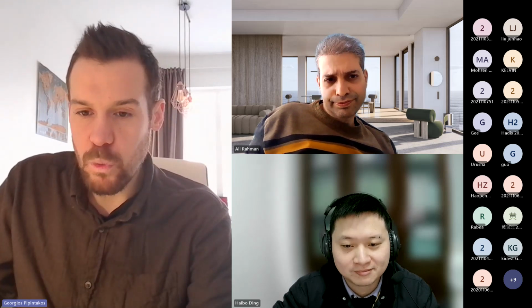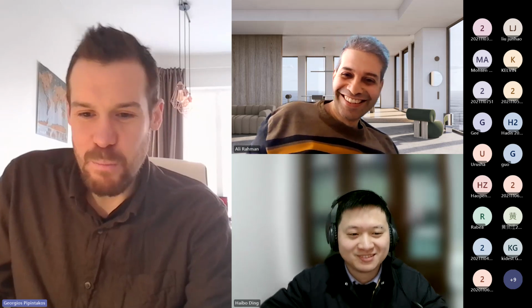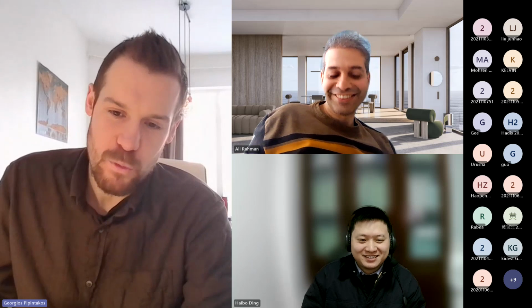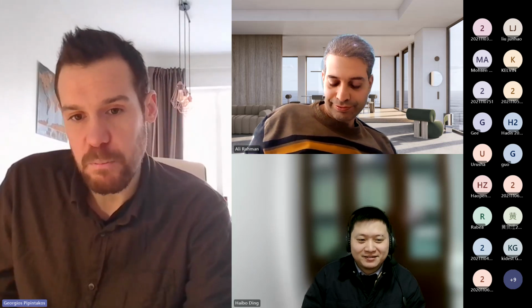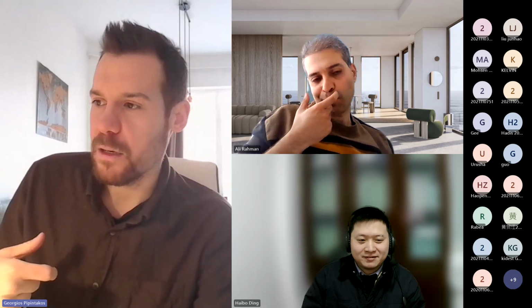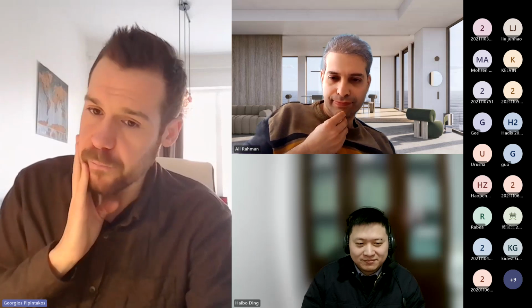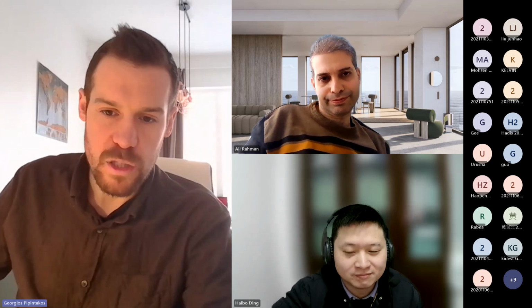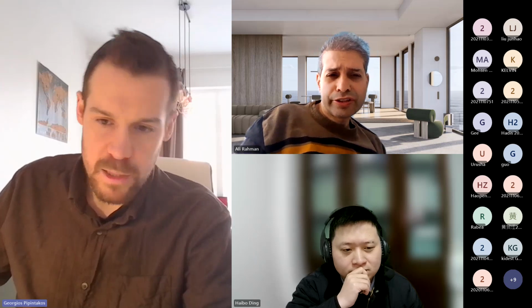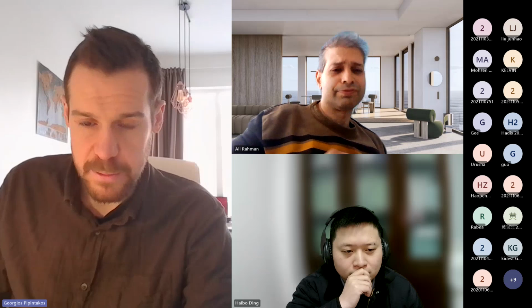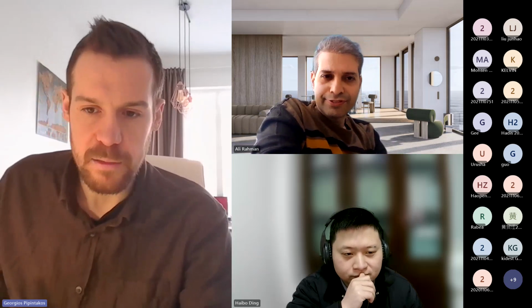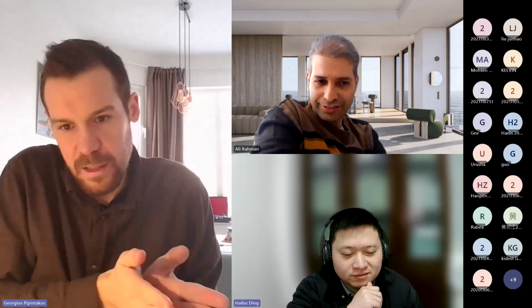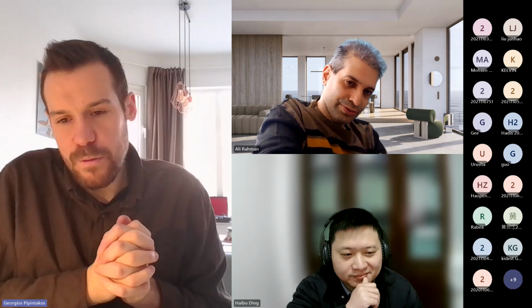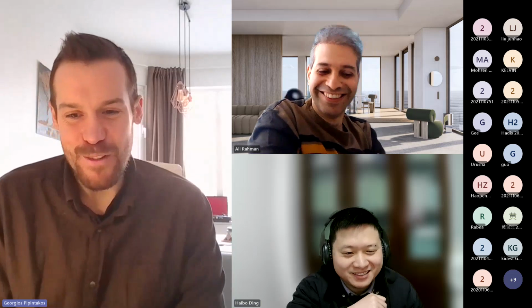So just maybe to give a diplomatic answer, I don't think that there is a best or worst. It's really based on what type of binder we really target. So if we study waxy binders, I think that physical hardening is the most important. If we study non-waxy binders or binders with low melting enthalpy, which also shows how much wax you have, then I think that oxidative aging is important. But on the other hand, there are researchers, probably you know, in Austria, that now study the reactive oxygen species and how they affect the aging mechanisms, which is, of course, another factor, as well as the UV light. I mean, of course, we need to simplify things sometimes to study the research. So, yeah, I think there is not a clear answer for which is the most important, let's say.